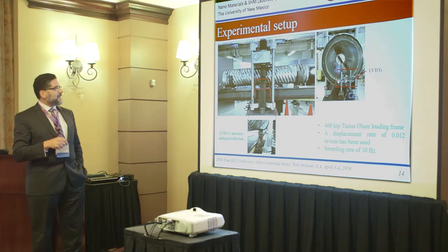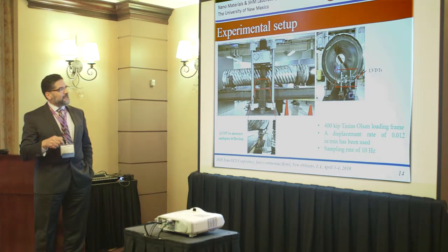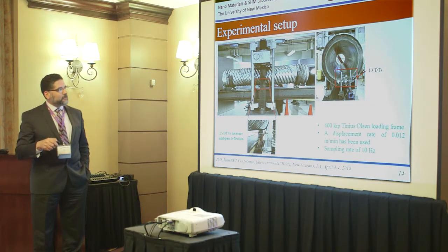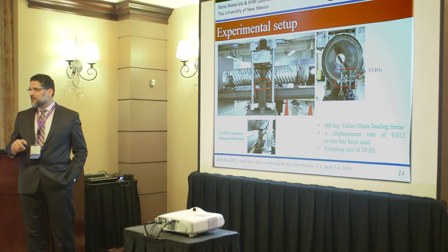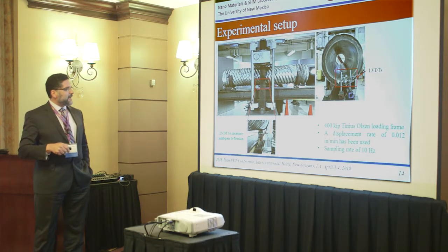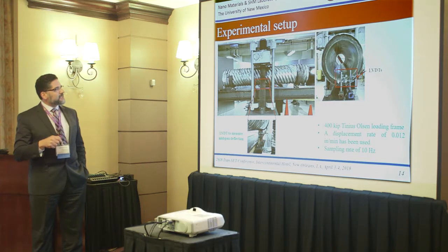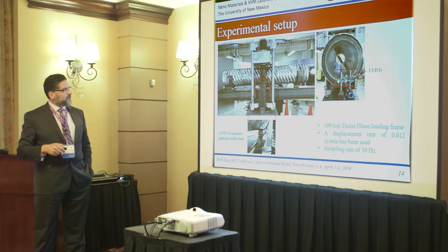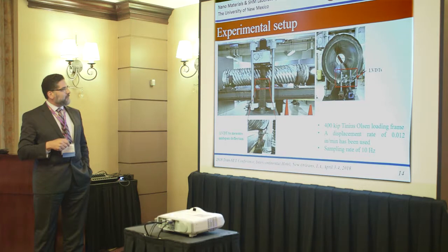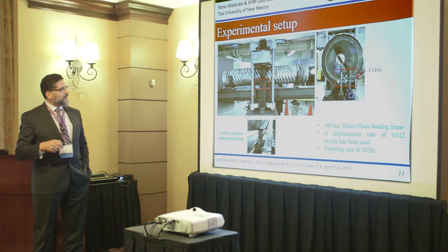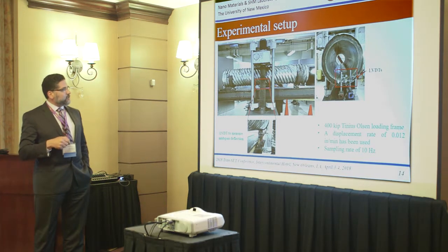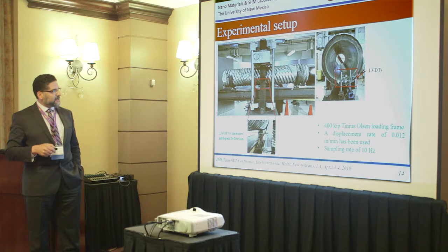So this is the steel pipe, as you can see, with the GFRP inside it, with the polymer concrete between them. We waited on it for a week before we did the testing. And we instrumented it; this is a 400 kip actuator. We made special bearing plates on both sides, the top and the loading plates, to allow sliding on this side and to allow having the same shape with the corrugation, here to be a pin and here to be a free side.